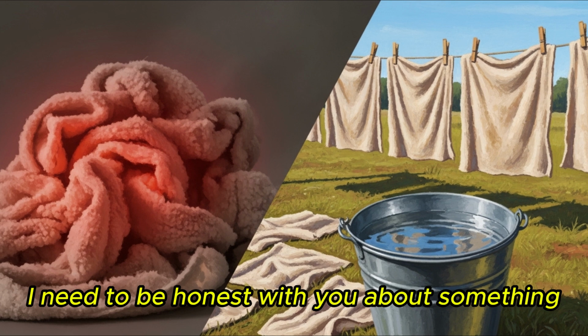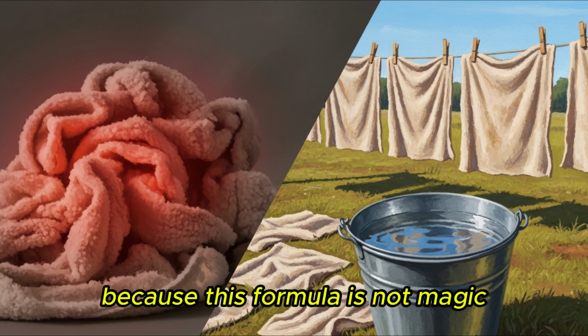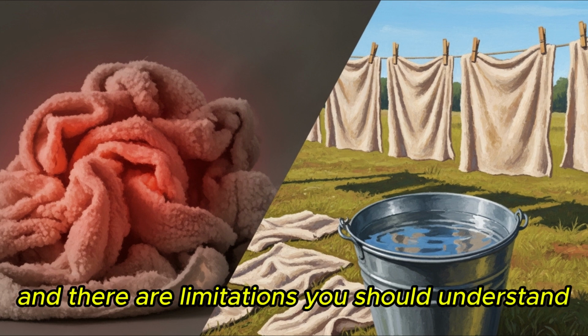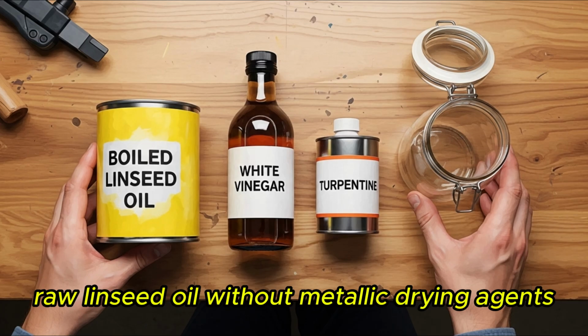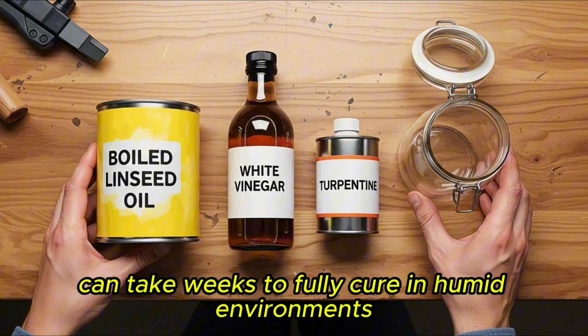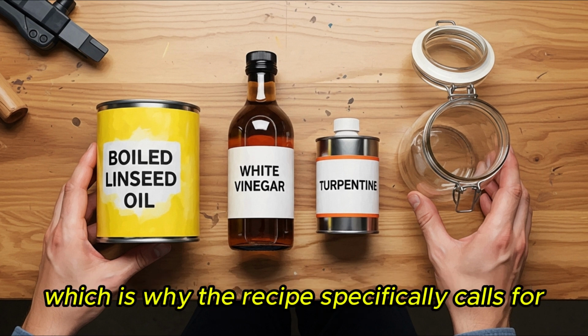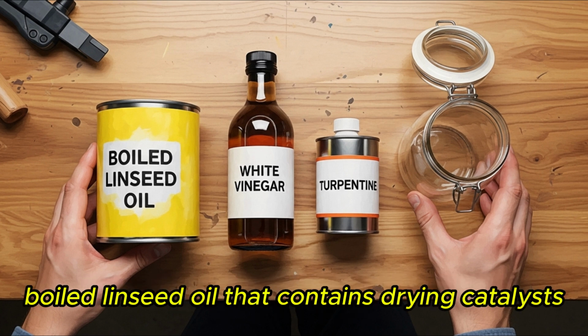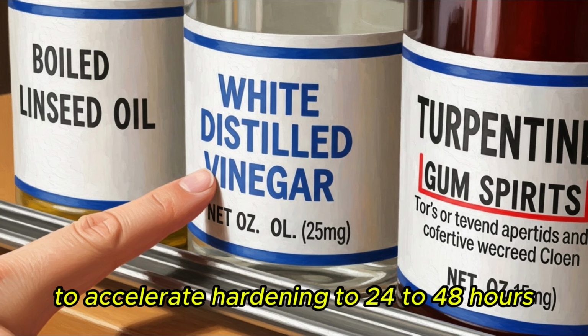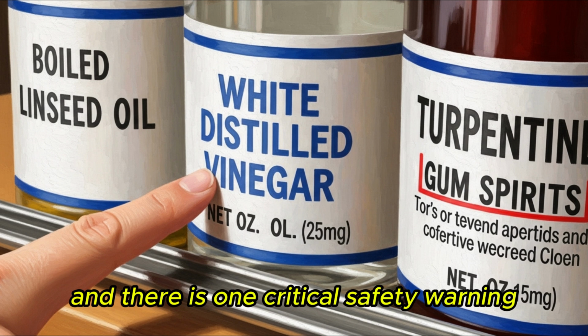I need to be honest with you about something because this formula is not magic and there are limitations you should understand. Raw linseed oil without metallic drying agents can take weeks to fully cure in humid environments, which is why the recipe specifically calls for boiled linseed oil that contains drying catalysts to accelerate hardening to 24 to 48 hours. And there is one critical safety warning that most do-it-yourself channels completely ignore.